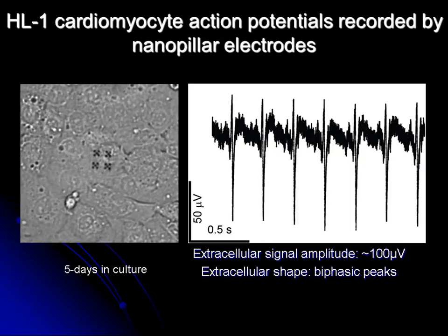What you can see in the movie to the left is that we cultured the cardiomyocytes on 25 nanoneedles. And indeed, as we show and also shown by many other labs, the nanoneedle does not interfere with the physiology of the cells. For example, the cardiomyocyte is still beating rhythmically on the nanoneedles. And to the right is the action potential we recorded from the nanoelectrode.